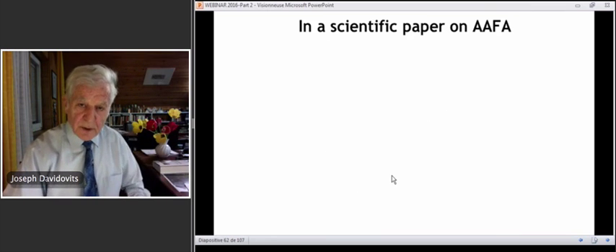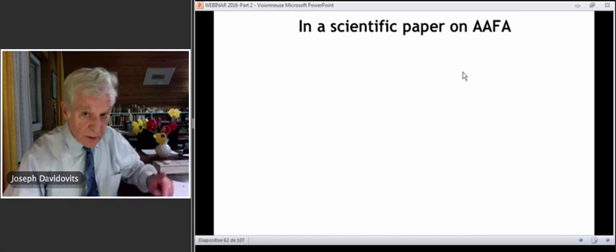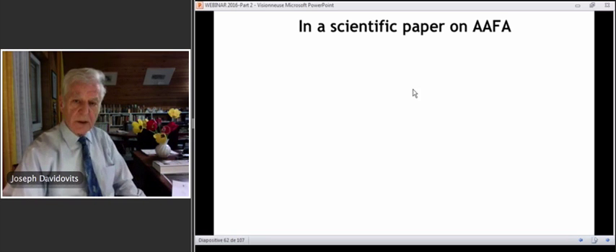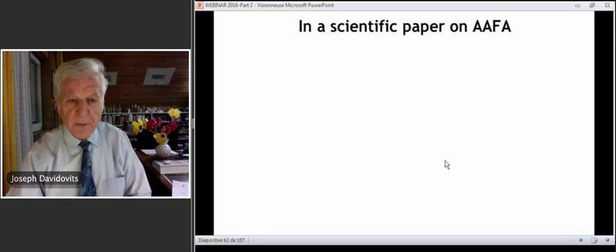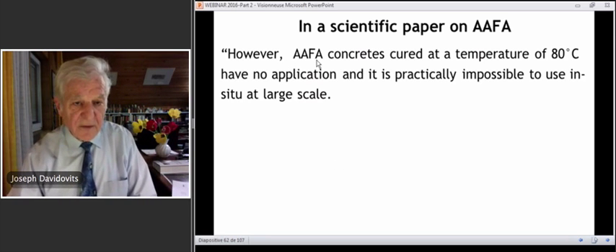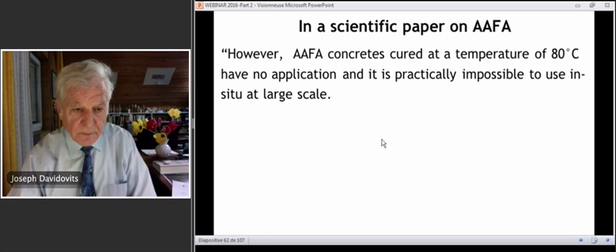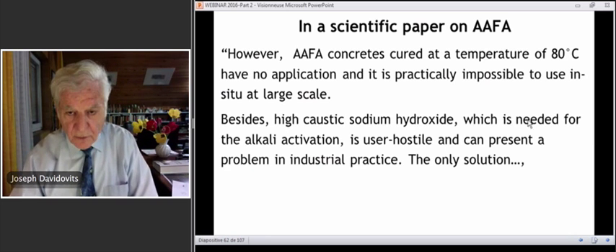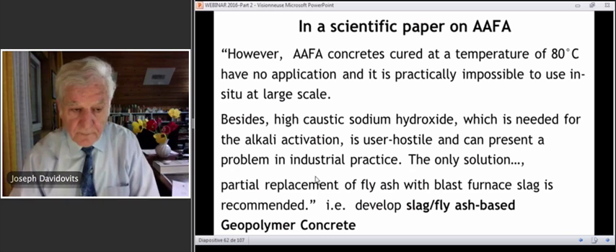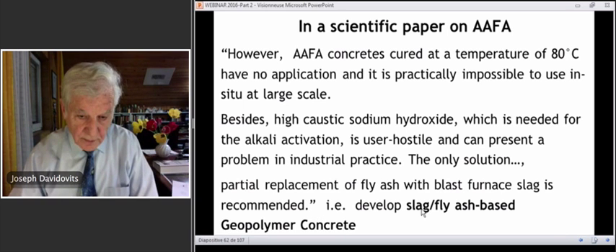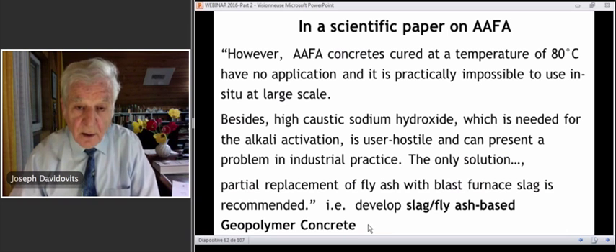I continue with a scientific paper dealing with alkali activated fly ash, not written by myself. I don't write papers on that topic, but it was written by another scientist. I don't put his name here. However, AAFA, alkali activated fly ash concrete cured at a temperature of 80 degrees C, has no application, and it is practically impossible to use in situ at large scale. Besides, high caustic sodium hydroxide, which is needed for the alkali activation, is user hostile and can present a problem in industrial practice. The only solution, if there is one, is the partial replacement of fly ash with blast furnace slag, which is recommended. That is, develop slag fly ash based geopolymer concrete.